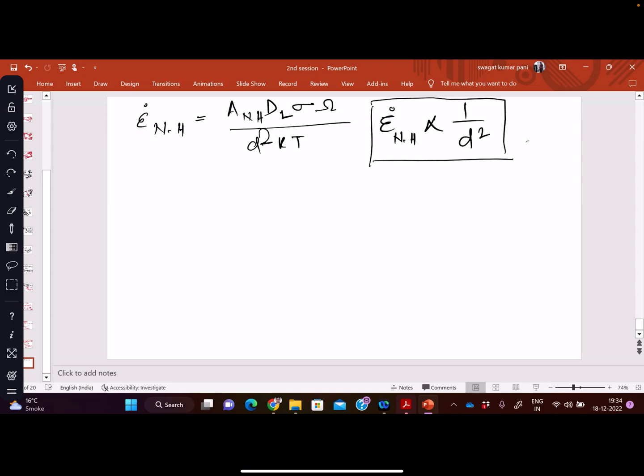So what is the strain rate? You don't have to remember this relation, just know the grain size relationship. There is some constant, the diffusion constant through lattice, stress, the interaction volume, d squared kT. All you have to remember is strain rate during Nabarro-Herring creep is proportional to 1 by d squared. And similarly for Coble creep, it is proportional to 1 by d cube. Nabarro-Herring occurs at high temperature, and Coble is relatively low temperature.